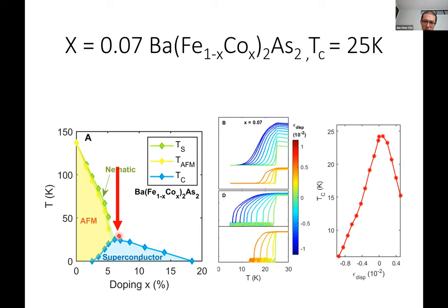But again, once you apply strain, you're already inducing some static magnetic order. So it's not clear to me that you can actually make a direct comparison to the kind of non-Fermi liquid theory people did before. When you apply strain, what you see is that the resistivity will actually have an upturn, even for the average resistivity, going from linear to showing an upturn as you're approaching the superconducting phase. Upturn, so it becomes more resistive on cooling? On cooling, yes.